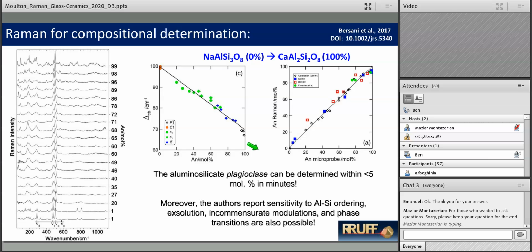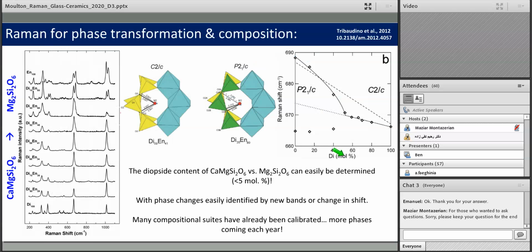And so here on the rightmost graph of your screen, the composition determined by Raman is on the y-axis, and that determined by microprobe analysis is on the x-axis. You have a very strong linear correlation between these two, suggesting that a Raman spectrum, which, again, you could take in maybe 10 minutes without much sample preparation, can leave you with a very accurate determination of the composition. Of course, if you're worried about minor impurities, you'll still need to do the microprobe, but this shows the amazing power of Raman on the composition of crystalline phases.